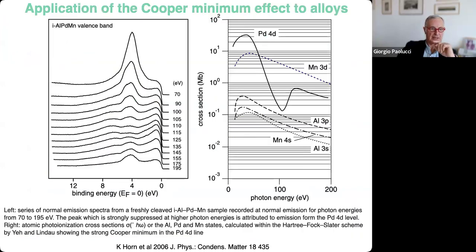For example, if you look at this real measurement from Horn and co-workers, you can see the behavior of the photoelectron spectroscopy spectra as a function of photon energy. So this is the valence band of an alloy, which is shown. So it's an aluminum, palladium, manganese sample.